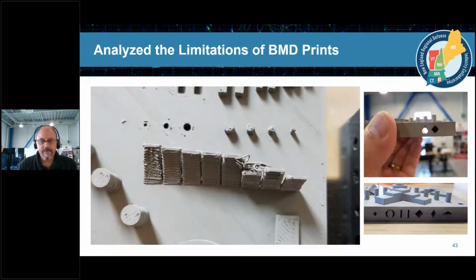And what we saw immediately were some limitations, some challenges with our desktop system. The extruded metal sometimes printed well, sometimes it didn't. In these overhang features, we had some collapsing. In our through channels, we had some areas where the sintered metal eventually wasn't able to be removed. And then we also had some challenges with inset features in things like circles and squares. But these were all things that were covered in the bound metal deposition guidelines that Desktop Metal provided.